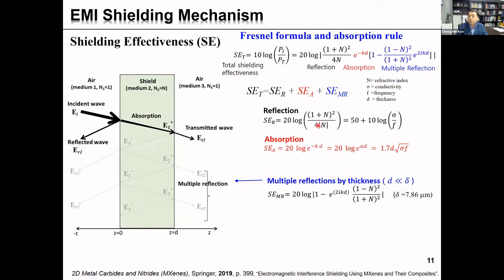Reflection, as you know, basically happens at the interface between two media having different refractive index or impedance, and absorption happens when the wave propagates in a shield. The intensity of the propagating electromagnetic waves exponentially attenuates with the propagating path length, which is the same as the sample thickness.